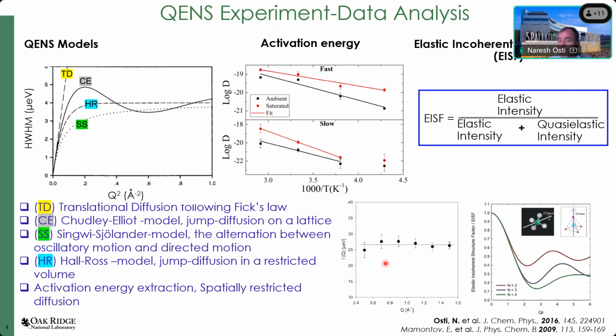At that time, you extract another important parameter, which you call the elastic incoherent structure factor, which is nothing but the ratio of the elastic intensity to the overall intensity. If you plot that as a function of Q, then depending upon the different types of models, you can extract the geometry of that confined motion happening within the material. That's another important parameter that you can obtain, and this is the beauty of this technique, where you can get the diffusion coefficient as well as the confinement size and the nature of the confinement. You can get both from this technique.